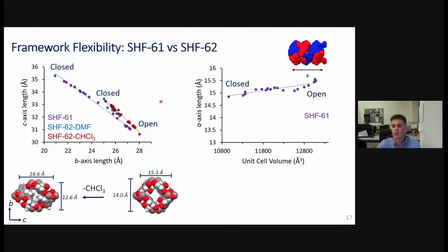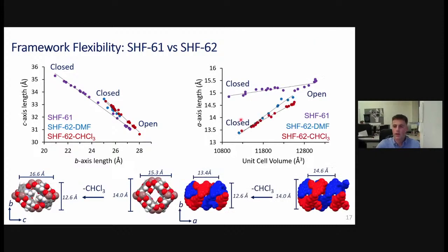And we can also map these changes in terms of looking at the A-axis against unit cell volume. So for Sheff61, we have this large change in unit cell volume, which is down to those changes in the B and C axis. But we see very little change in the A-axis, so that's the compression of this helical-like arrangement. However, when we look at the same data for Sheff62, the modified framework, what we see is a similar change in overall unit cell volume, but we now have a much more pronounced change in the A-axis.